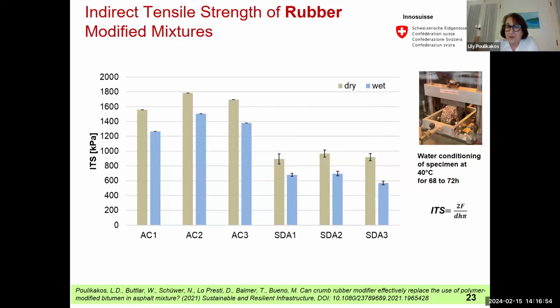I can show you some examples of that here. You see the results of the indirect tensile strength for 6 mixtures. 3 are asphalt concrete and 3 are SDA, the semi-dense asphalt. You see, of course, the strength is lower for the semi-dense asphalt, both in dry state and wet state. AC1 and SDA1 do not have any rubber in them, and 2 and 3 in both cases do have some amounts of rubber. You see that in almost all cases, there's an increase in the strength in dry and wet state. Only in one case was there a decrease in the wet state, and that SDA3 had more rubber in it. The quotient of that would be the ITSR, the indirect tensile strength ratio, and 5 of the 6 passed the requirement in Switzerland.